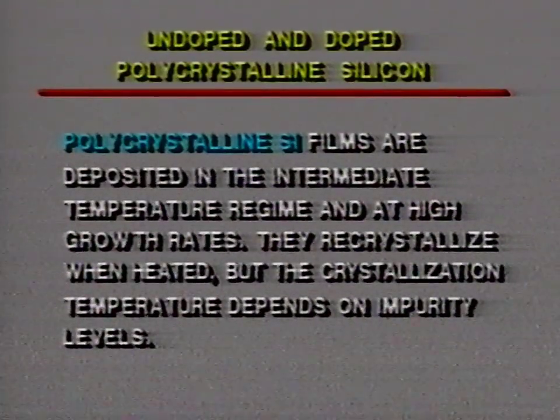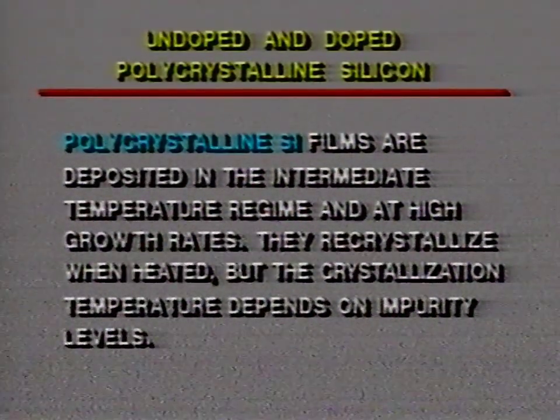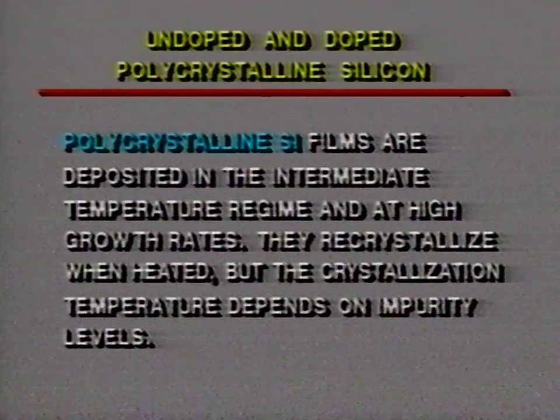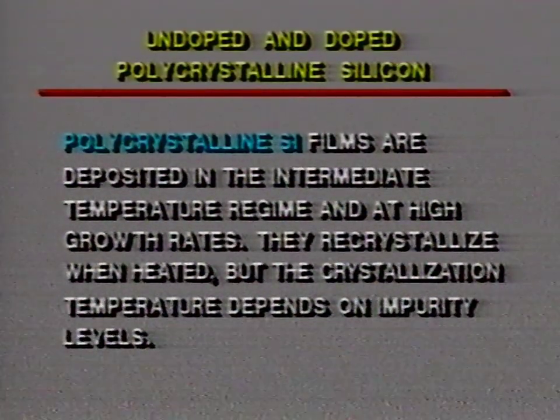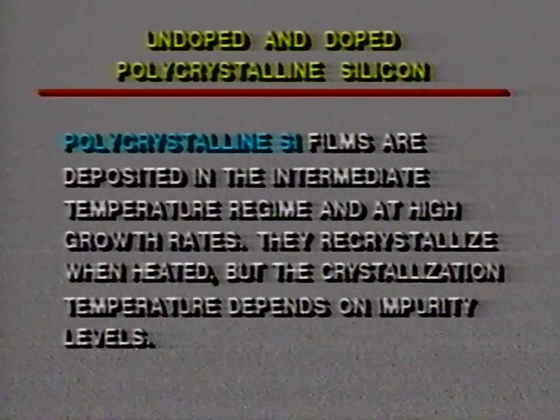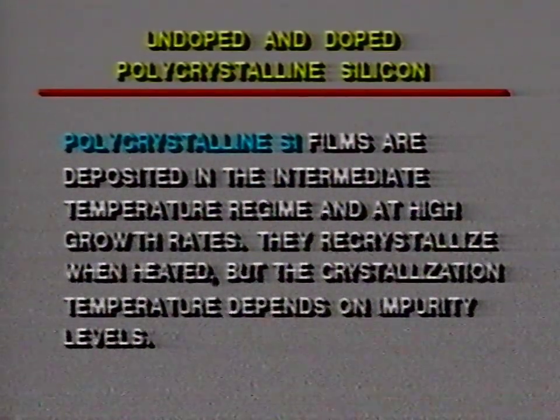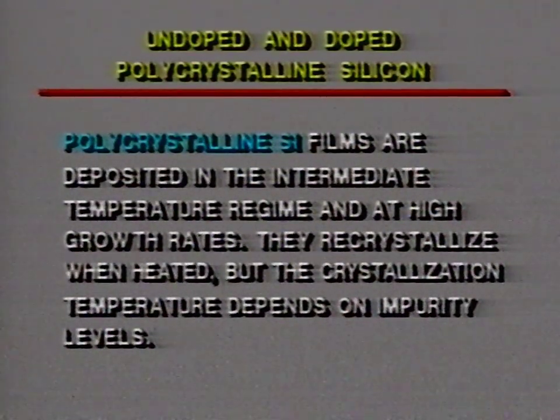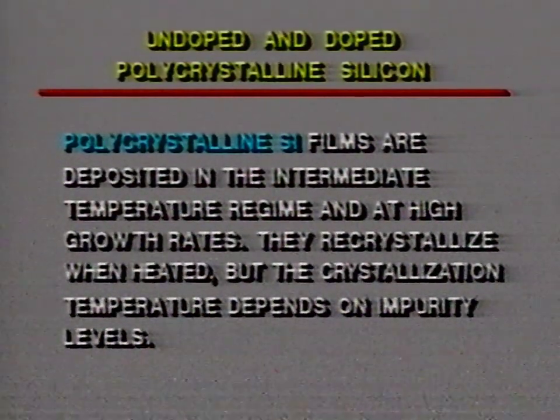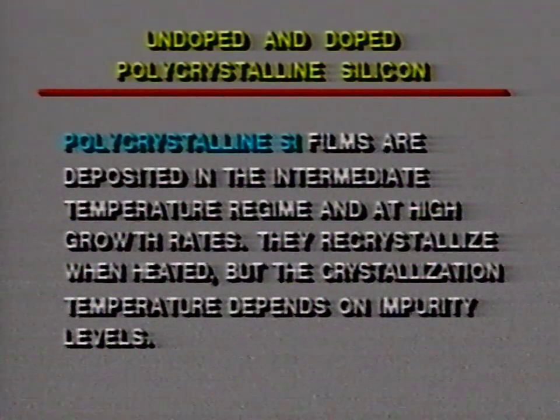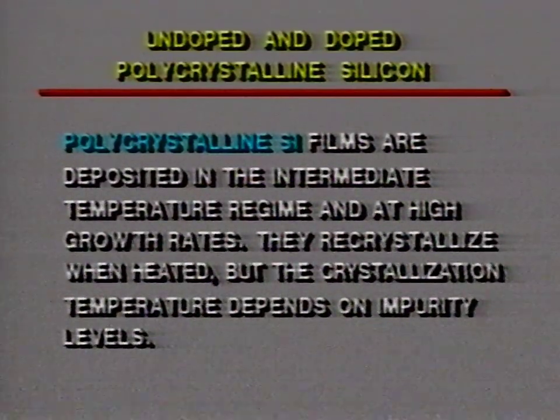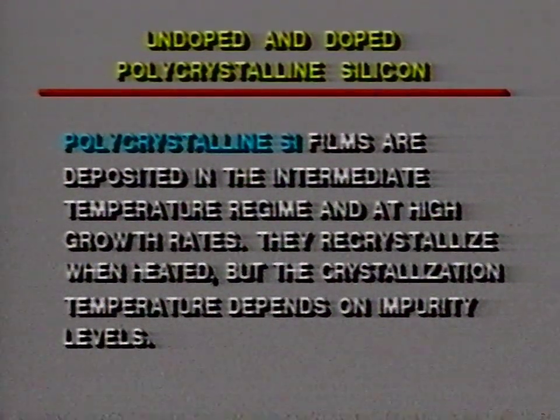Now there is some more here on the polycrystalline silicon, both undoped and doped. And what we can say here is the polycrystalline films, as deposited in the intermediate temperature range, well, that's what generally is done. They are deposited in the intermediate temperature range, and they are obtained at fairly high growth rates. They crystallize when heated, but the crystallization temperature depends on the impurity levels in the films, so we cannot make a general statement here.